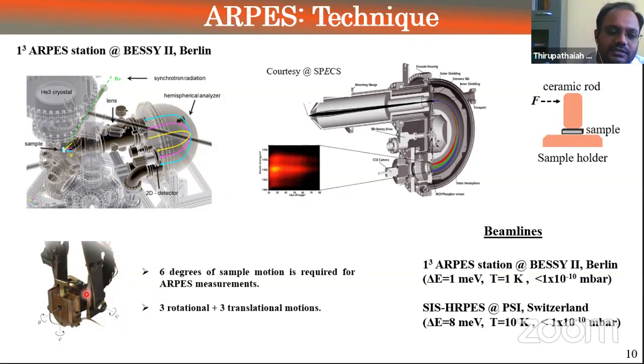For ARPES, of course, we need a manipulator or cold finger with 6 degrees of motion. For standard XPS, you don't need any degree of rotation, but for ARPES, we need a minimum of 6, or maximum 6. Out of them, 3 are rotational and 3 are translational. If any one of them is missing, then you are compromising on moving around your 3D Brillouin zone.